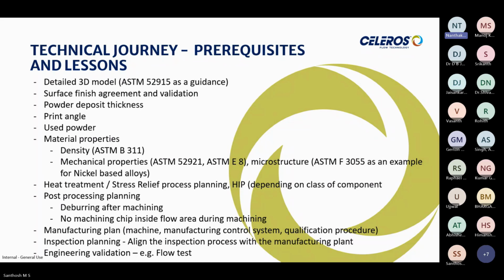The second is about surface finish. And I say here we need an agreement and a validation. When we talk about surface finish, most of our conventional drawings have a listed surface finish, which probably is not needed in many cases, or in some cases it's mandatory. We are not sure, because it's conventionally machined and finished, or EDM and finished. So the conventional drawing would have that particular finish. But in terms of a real functional need, that surface finish needs to be revisited when we move to additive manufacturing. But in our case, there was no chance of reducing or compromising on the surface finish. We needed a minimum finish because there was flow involved in those passages.